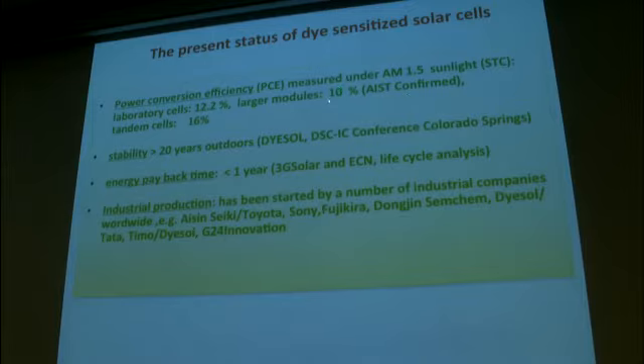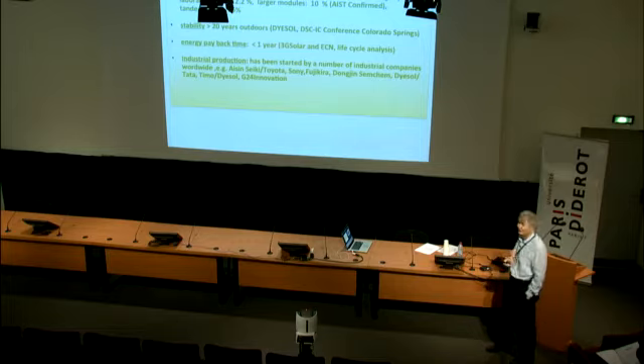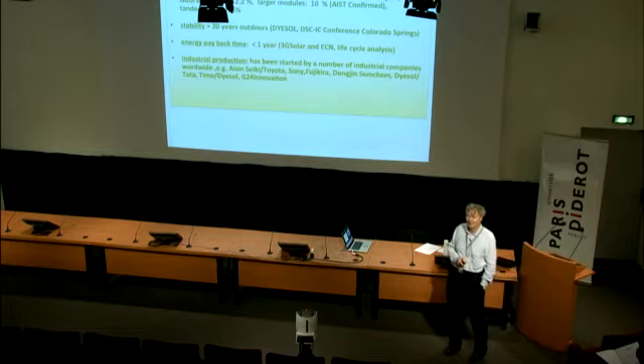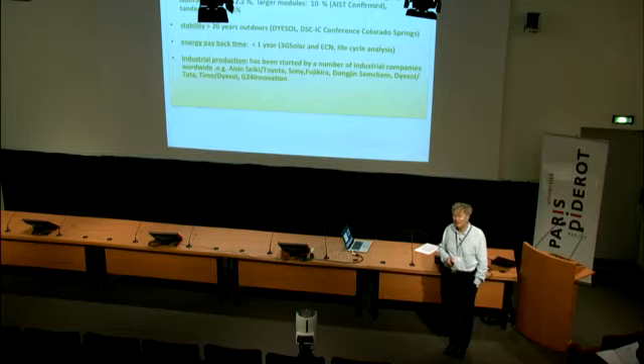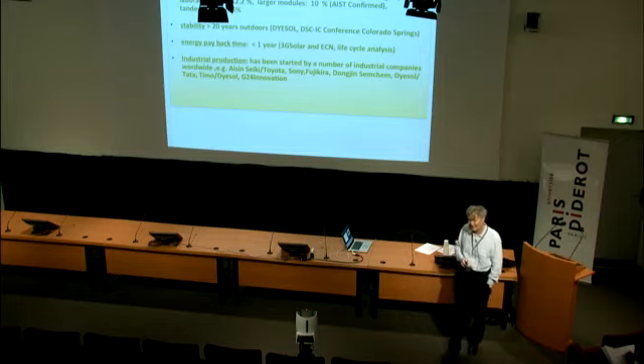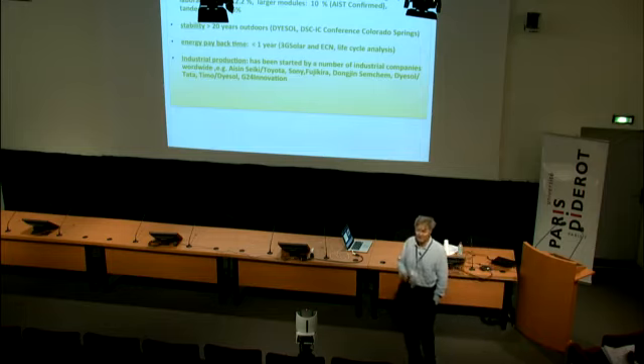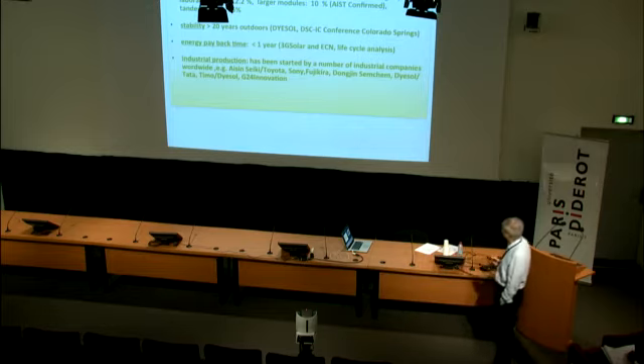This is a very important figure. You've got to have a good efficiency on the scaled-up version of the cell. It's not enough to measure tiny little devices of, say, 2 or 4 square millimeters, and then say, well, I've got now 8%. This is not enough. You have to be able to scale it up, and not only that, you have to be able to produce the cell in an industrial process that has a yield of nearly 100%. And it has been one of the drawbacks of CIGS. CIGS is hampered by the fact that the yield is low, 50%. And so this is very important.